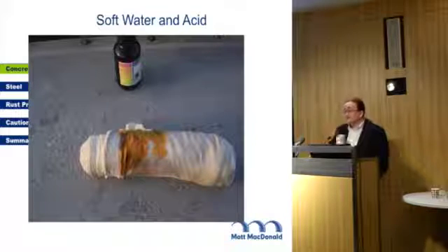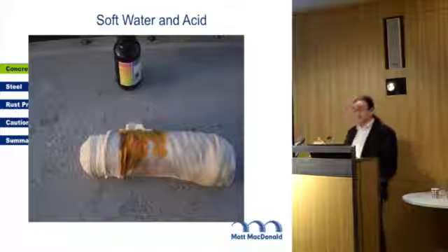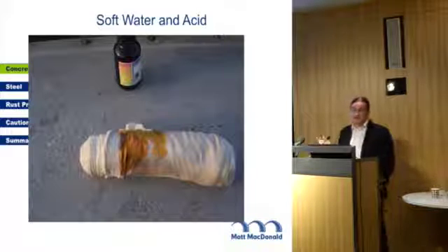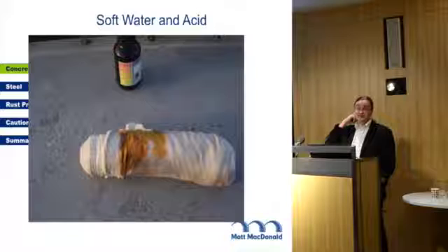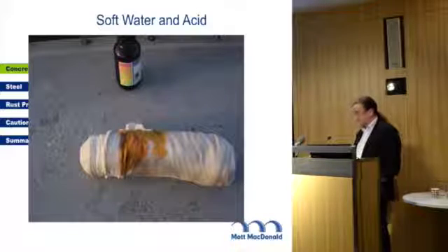Durability-wise, that's fairly bad. In this case, it was on 110 mil wall thickness, so basically they get to the steel in about 3 years, get through the entire wall in about 10, because they put a lid on it to please the neighbours.